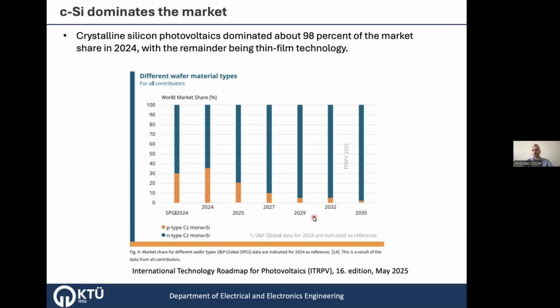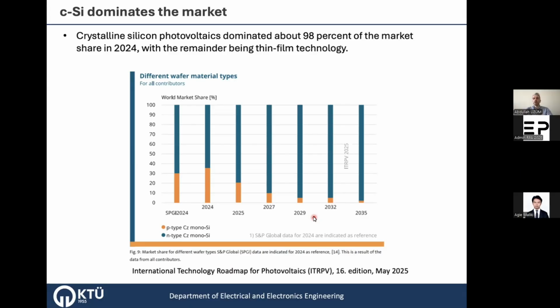It is a well-established, well-known, state-of-the-art technology, and reproducibility is very high. That's why it has very good advantages. And that's the thing, actually. We try to use silicon in tandem cells because silicon has a theoretical limit with a single junction, and it has reached that limit at around 30% efficiency. To exceed this efficiency, we need tandem-like structures. And because we know crystalline silicon manufacturing very well, and the lines are established everywhere, we try to use this technology and build on it for cost efficiency.